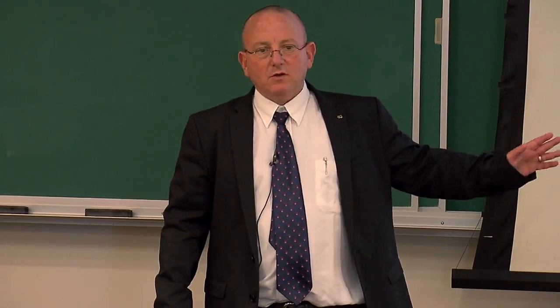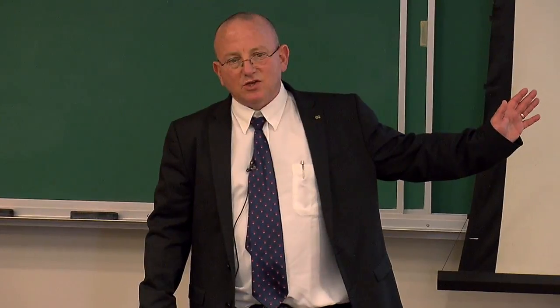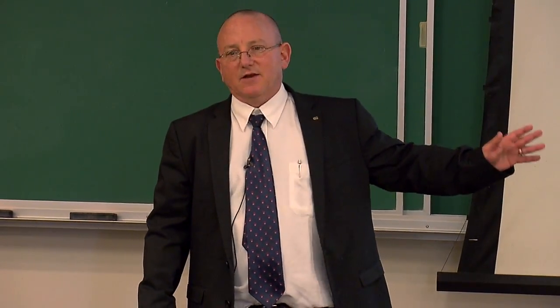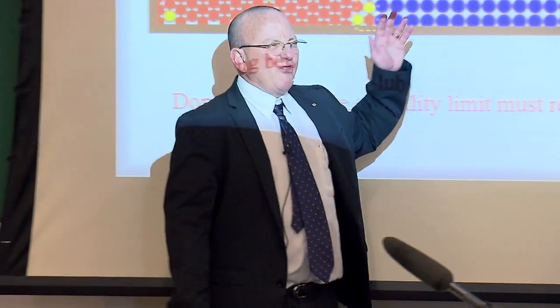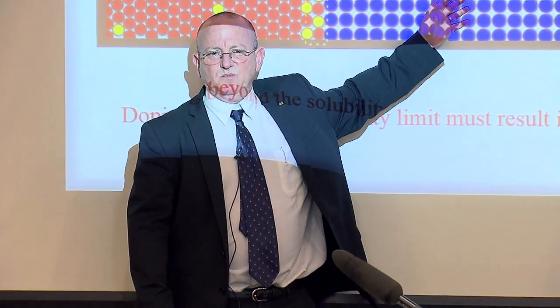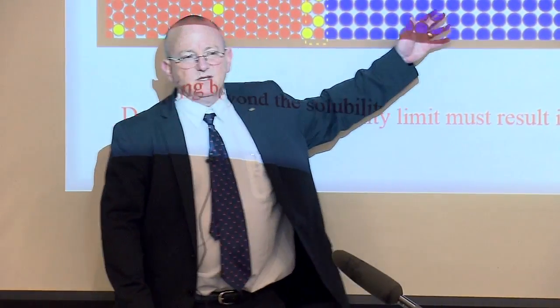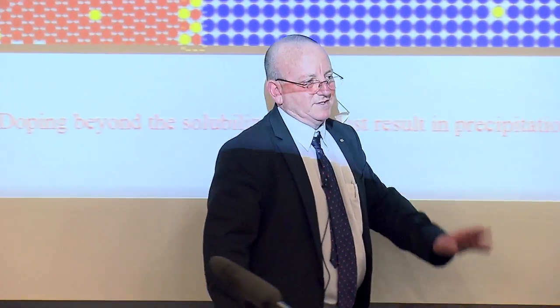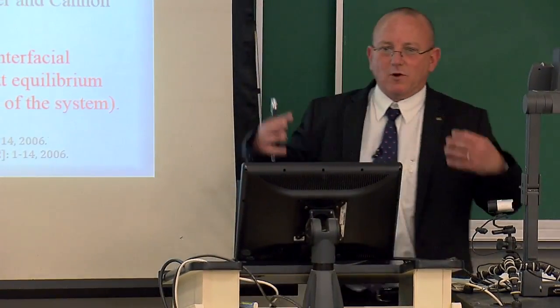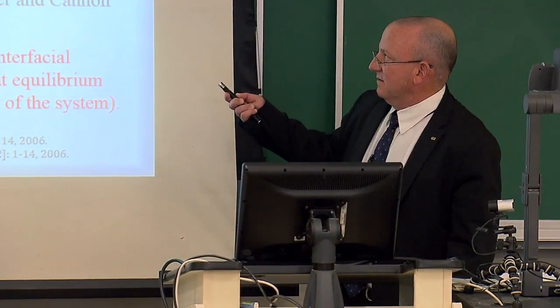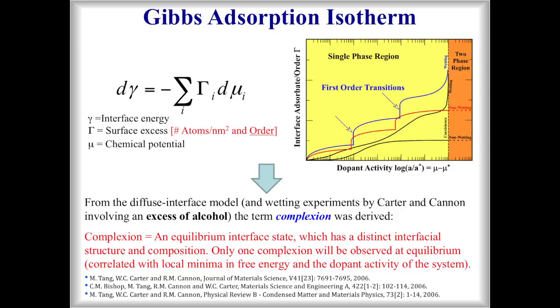The Gibbs adsorption, segregation, doesn't talk about that. Segregation is not the blue stuff throwing the yellow out because it doesn't want any more in there, so it has to precipitate. Segregation is the yellow stuff going to the interface because its presence there reduces the interface energy. Okay? What I just showed pictorially is exactly this. Okay? And these jumps or discontinuous transitions